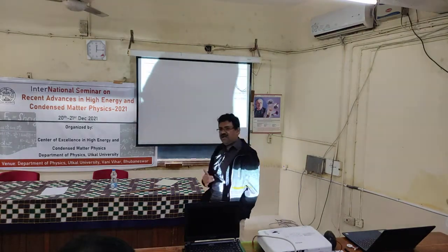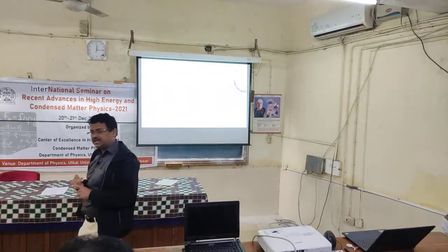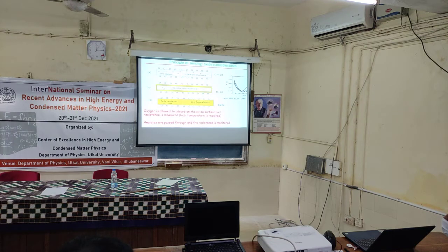So now probably it's clear why we need a moderate temperature for tin oxide, and what the principle is. You have to pass oxygen at constant level, and then you expose it to the gas which one would detect. So this is how it is for tin oxide.